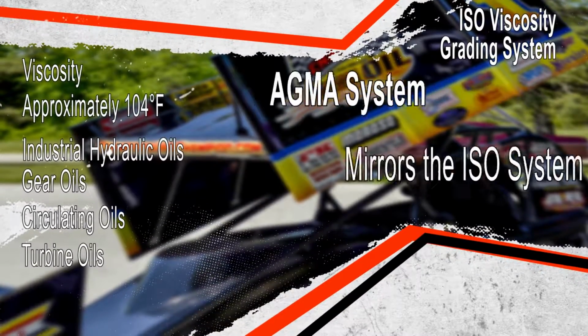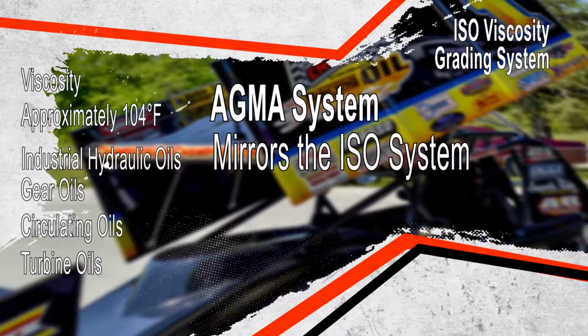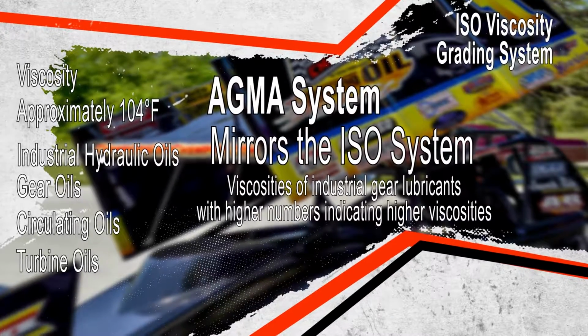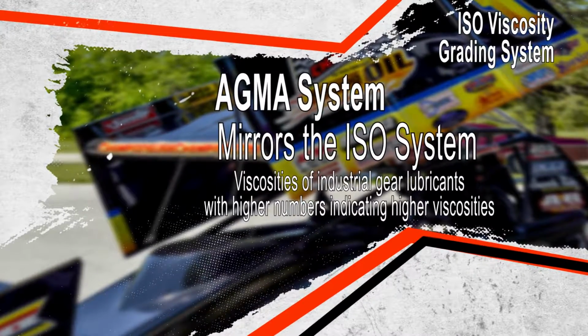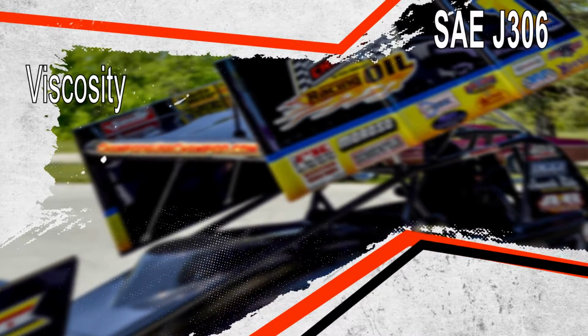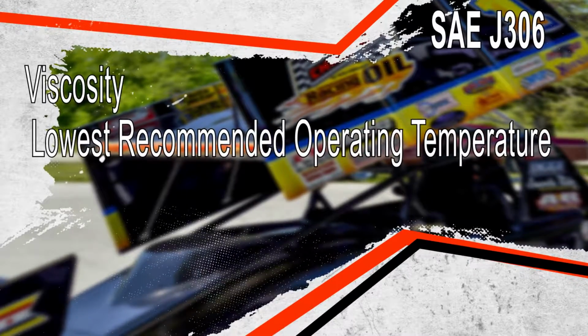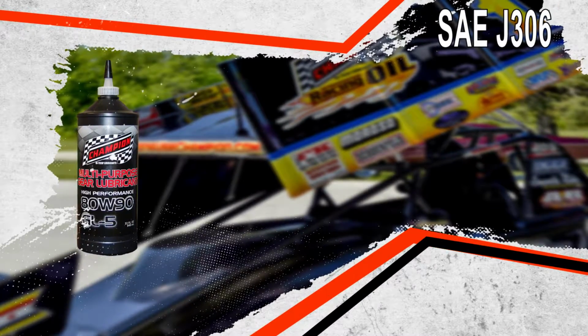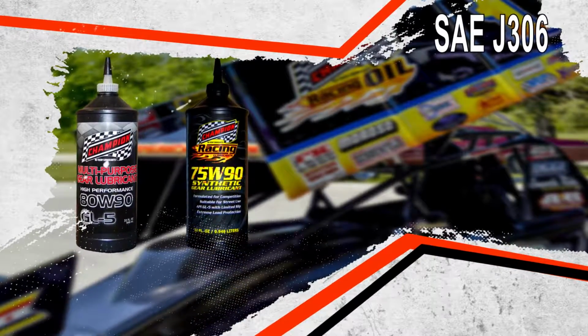The AGMA system mirrors the ISO system and numbers the most common viscosities of industrial gear lubricants, with higher numbers indicating higher viscosities. SAE J306 categorizes automobile gear lubricants by their viscosity and by their lowest recommended operating temperature. For example, an SAE 80W90 or an SAE 75W90 can be operated at temperatures as low as -40 degrees Fahrenheit.